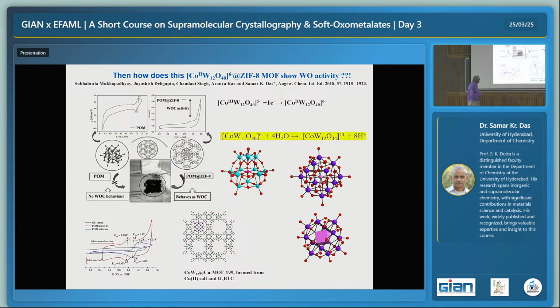Here we could locate it, and we found that earlier the cobalt was tetrahedrally bound, cobalt 4, but here we found 8. Cobalt is connected to 8 oxygens, as if it is inside a cube. Then naturally the question comes: let's say these tetrahedral oxygens are disordered over 2 positions. If one oxygen is half occupancy, disordered over 2 positions, it will look like it is octahedral only.